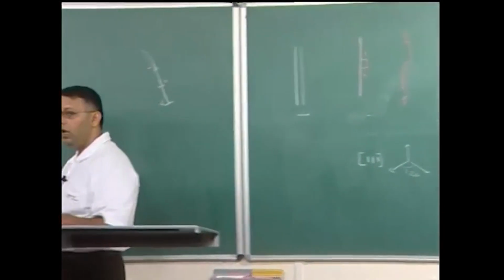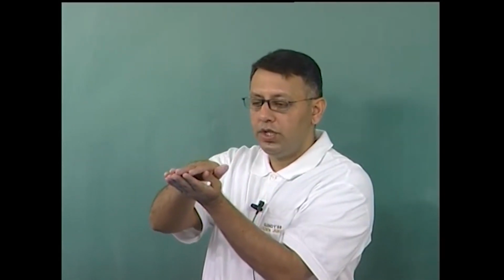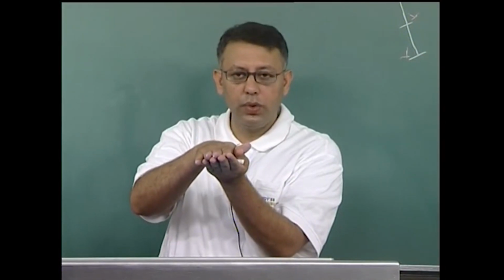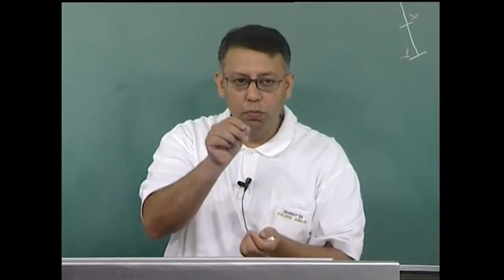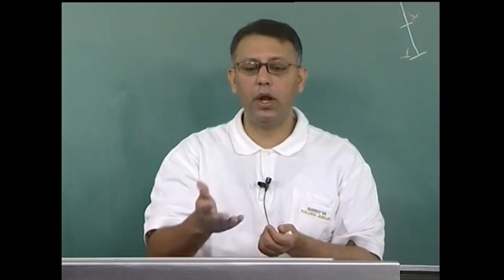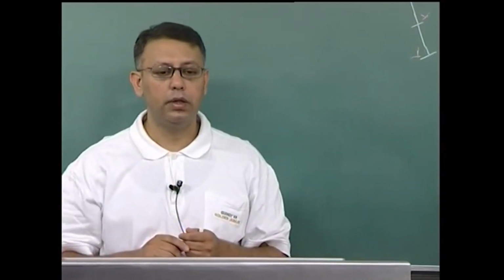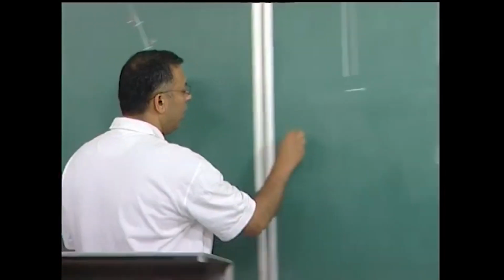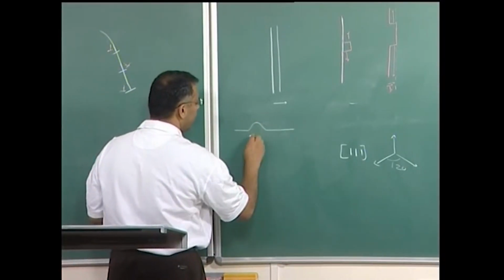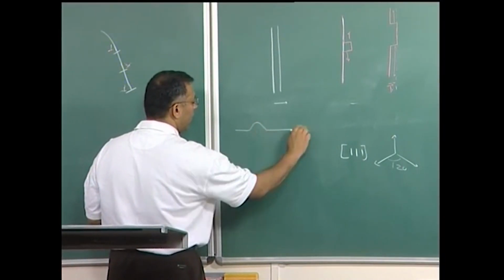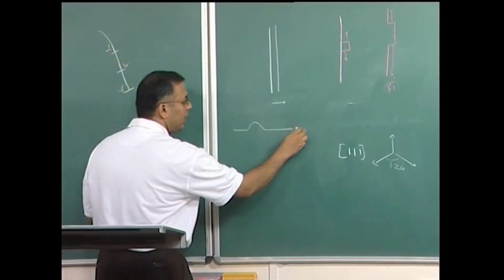Therefore, I can see that the dislocation itself is a medium by which you can avoid the shearing of the entire crystal. You reduce that problem of shearing of the entire crystal to small regions in the crystal, and typically the analogy given is a fold in a carpet. You make a fold in a carpet and roll this fold down to get a little elongation, and I can make repeated folds to move the carpet.